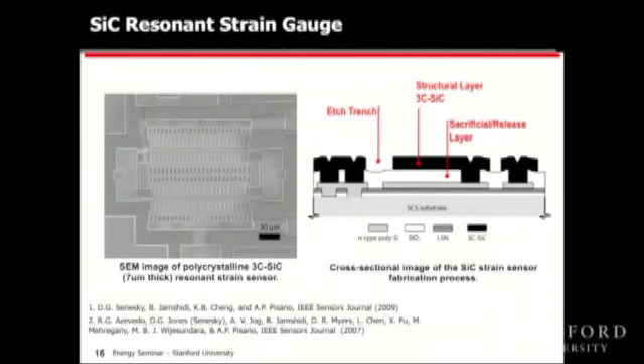This is a cross-section of the fabrication process. Again, we use silicon substrates and polysilicon carbide thin films that are micromachined, and then we release the underlying sacrificial material to have these long released structures. So this is a hovering structure on top of a silicon substrate.